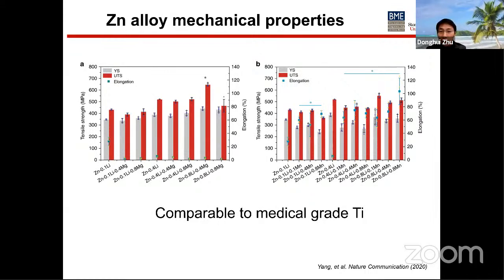Lately, new zinc alloys have been developed showing superior mechanical properties. If you look at these two figures, especially the zinc-lithium alloys or zinc-lithium-magnesium alloys, their mechanical properties can reach as high as those of medical grade titanium. This opens a new window for using magnesium or zinc to potentially replace some titanium-based implants later on, providing very good mechanical properties in zinc-lithium or zinc-lithium-manganese alloys.